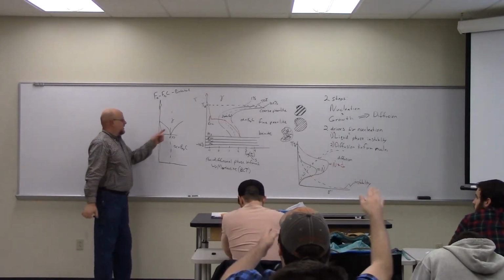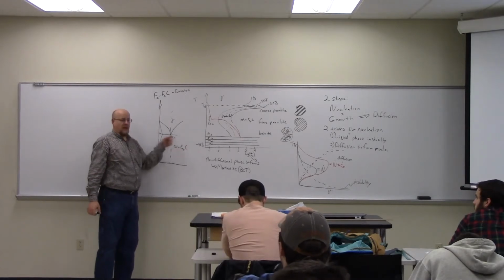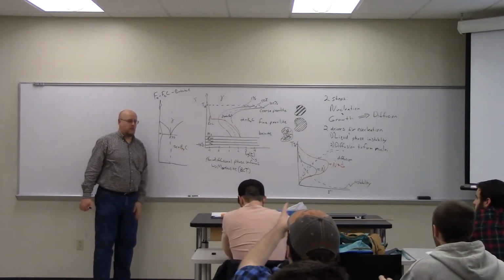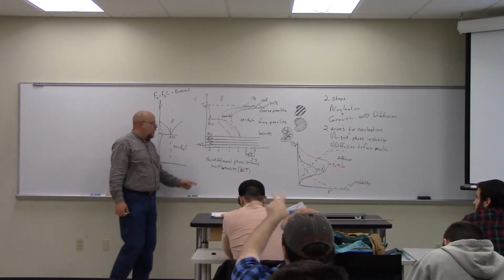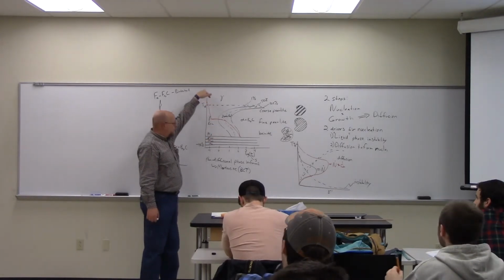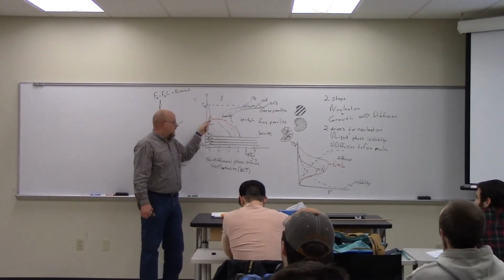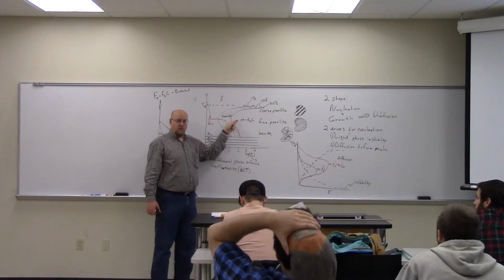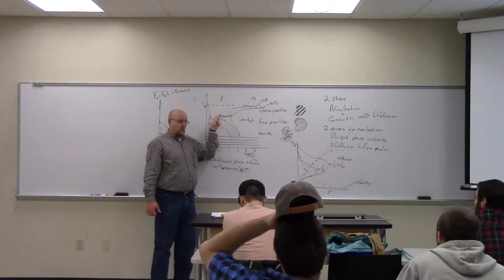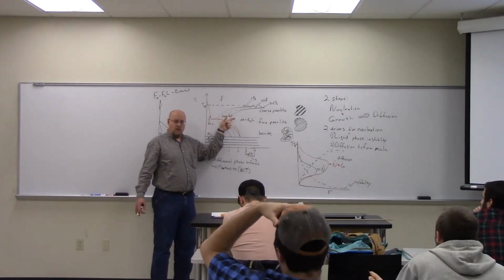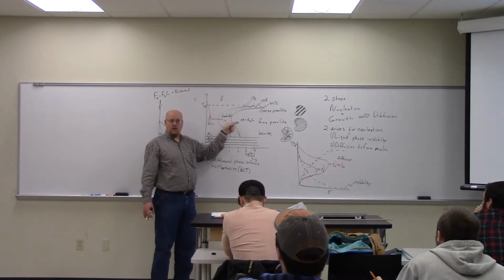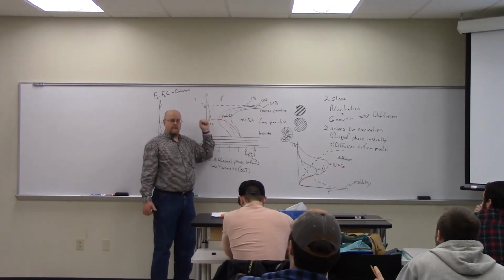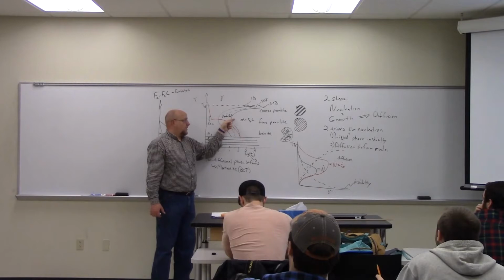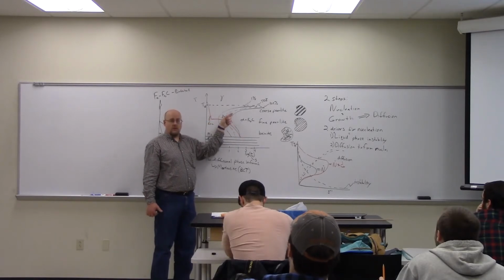Martensitic transformation, because alpha is a BCC material, can only go from gamma to martensite. It cannot go from alpha plus Fe3C to martensite. So those lines really shouldn't go past the height. No, it does, because this only covers down and to the right. Now, I've already gone 100% transformation, right? Once I've gone to that point, I'm done. Once I've crossed the 100% line, I'm done. So you can't go down to the right and then down again. I can, but it's not going to change anything. Once I cross that 100% line, I'm done.